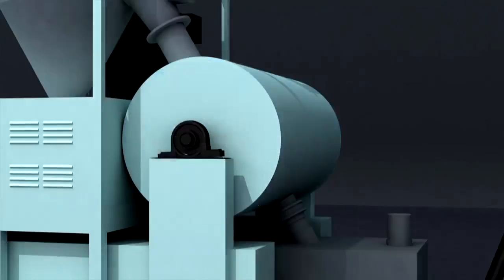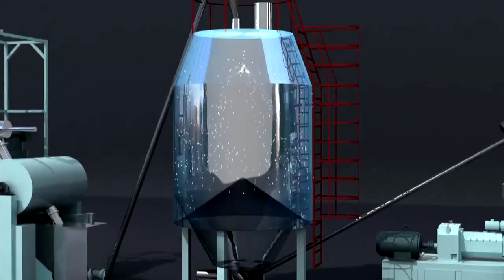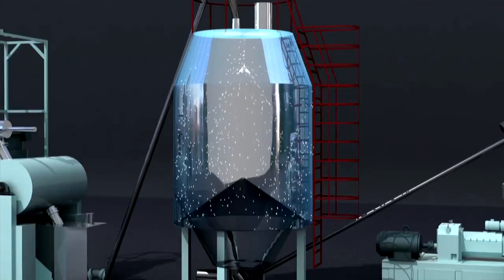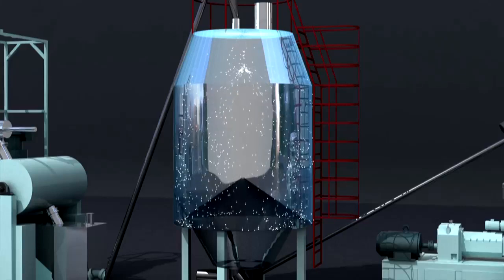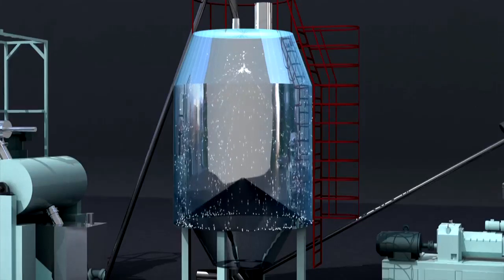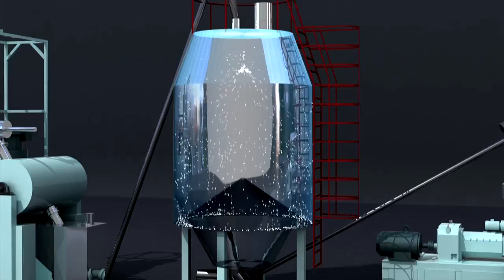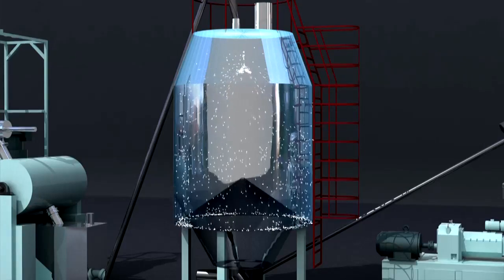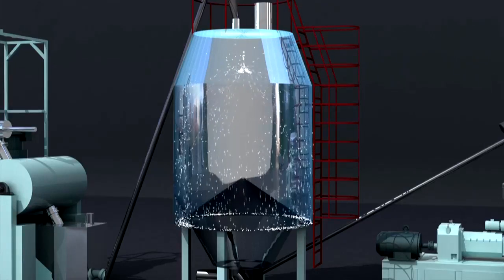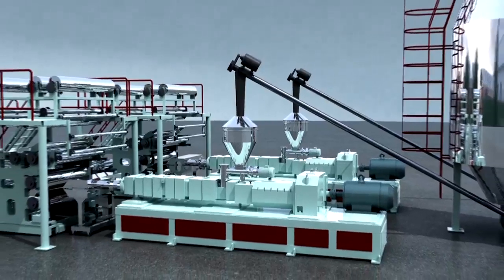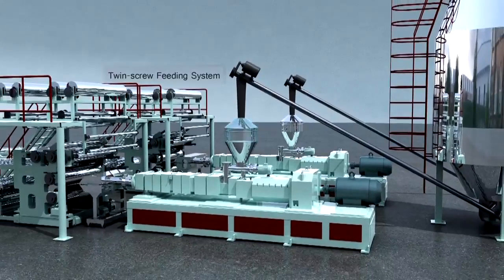After reaching the use requirements, it will be automatically discharged into the cold mixer, preventing plasticization and decomposition in advance, then rapidly cooled to about 45 degrees Celsius, and then discharged to the silo, and the discharged material will enter the twin-screw feeding system through the screw feeder at a constant speed.